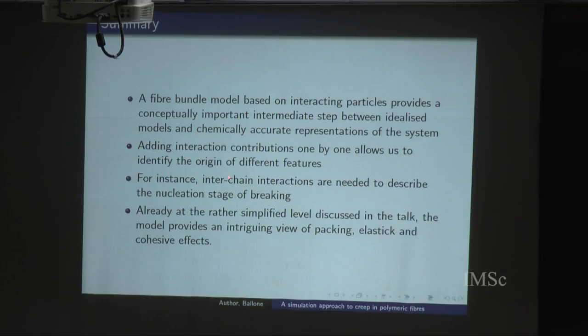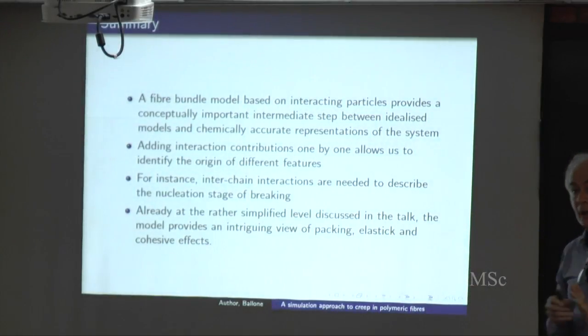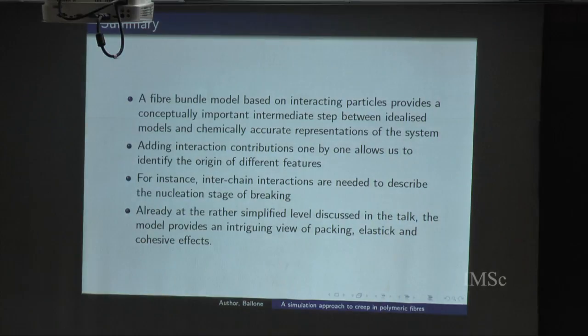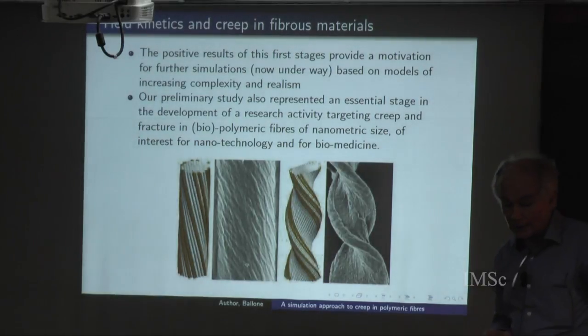For instance, interchain interactions are needed to describe the nucleation stage, how the breaking starts, nucleates or doesn't nucleate in the system. There are plenty of features that I didn't have time to discuss, but we see many important, intriguing phenomena like the effect of packing, in the sense that under some conditions our samples are partly crystallized, essentially because of the size of the particles. And so we have packing, we have elastic properties, we have cohesive effects. So it is much richer than the original bundle.